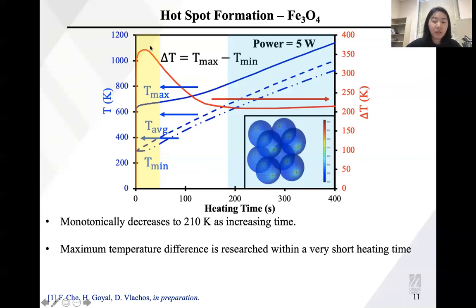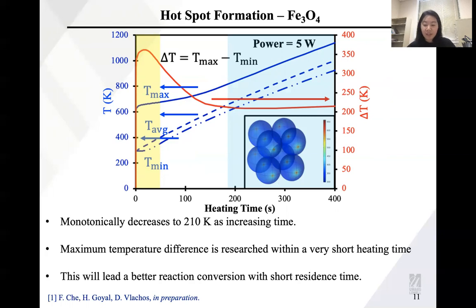It reached the hotspot at the beginning, at 20 seconds after heating, and that is the maximum temperature difference between the hotspot and the rest area of the catalyst particles. And you can imagine if your catalyst packed bed has these hotspot formations, it may lead to a better conversion because of this high temperature with short residence time as compared to conventional heating.